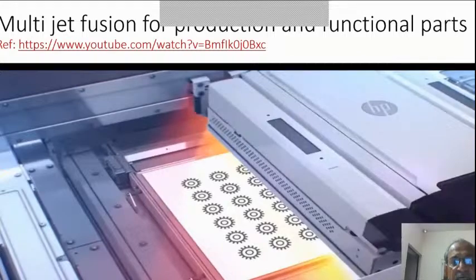There is a new technology which is called multi-jet fusion. This has come from a company called Hewlett Packard. This is a very unique technology because here what they do is spread the powder, which could be a nylon powder or could even be a metal powder. Now they have launched a metal machine as well. In this, the powder gets spread in a thickness of 80 micron, and instead of heating it up with a laser or treating it with just light, they have